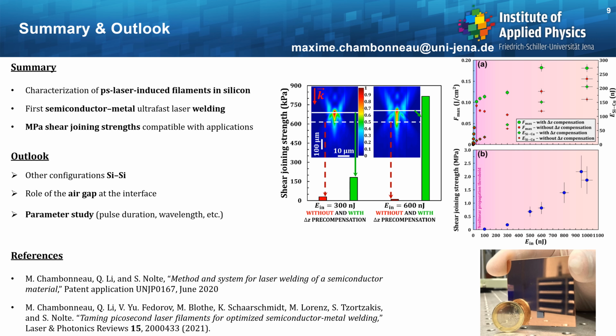To summarize, we have characterized the nonlinear propagation inside silicon for picosecond laser pulses. By precompensating the nonlinear focal shift, we have achieved the first semiconductor metal ultrafast laser welding. We have obtained megapascal shear joining strength that are compatible with applications. And to go further, we would like to try other configurations like silicon-silicon. We also would like to evaluate the role of the air gap at the interface. And finally, we will carry out a parameter study as a function of the pulse duration, the wavelength, and so on.